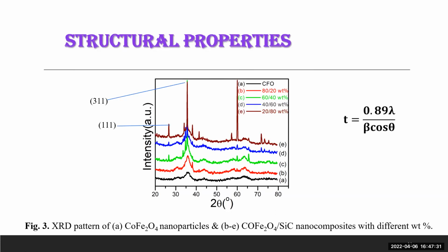Then the crystalline size was calculated using the Scherrer formula, that is D equals 0.89 lambda upon beta cos theta, which was estimated for cobalt ferrite nanoparticles at around 3 nanometer, and for the other weight percents of the cobalt ferrite silicon carbide nanocomposite respectively 5 nanometer, 6 nanometer, 11 nanometer, and 18 nanometer. So we can conclude from this that as we increase the doping of silicon carbide with the cobalt ferrite, the particle size also increases. Then we move towards the morphological study of our material.